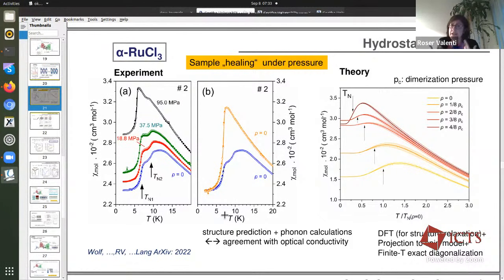In the rhombohedral structure, where you have higher symmetry, it has an angle tilting. And the difference between these two structures has to do with indeed these stacking faults that people are talking about. Many people don't know whether they have a C2/m structure or a rhombohedral structure. The way that people are associating the crystal structure with whether they are more in the rhombohedral structure or in the C2/m is by looking at the magnetism, by looking at what kind of magnetic phase transitions they have. If they have one very clean magnetic phase transition at low temperatures, this is associated with fewer stacking faults, so you may have this rhombohedral stacking.